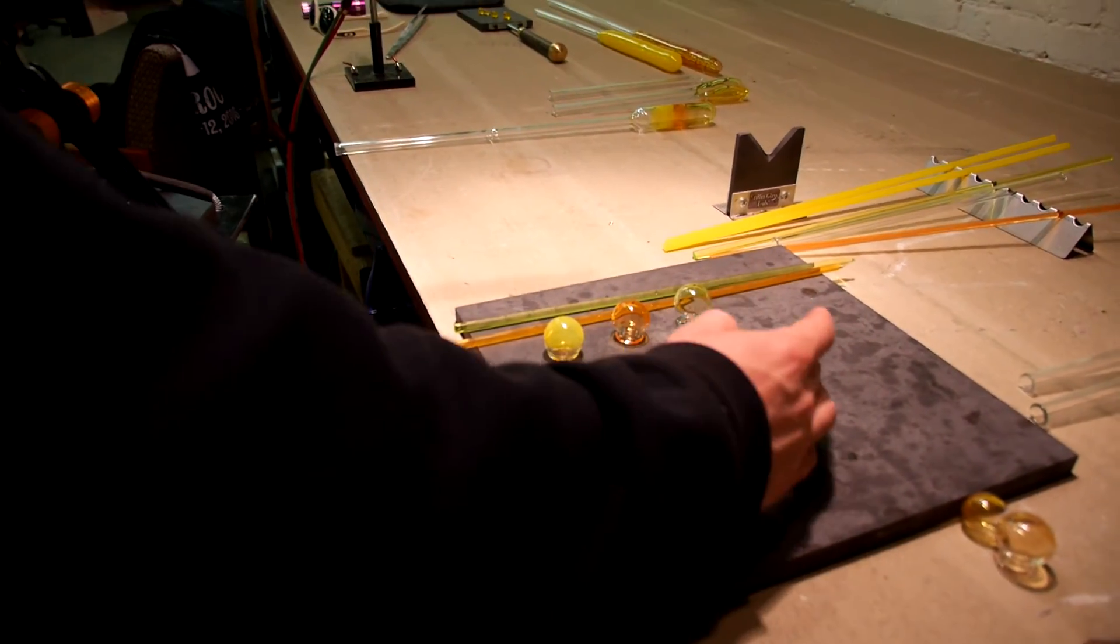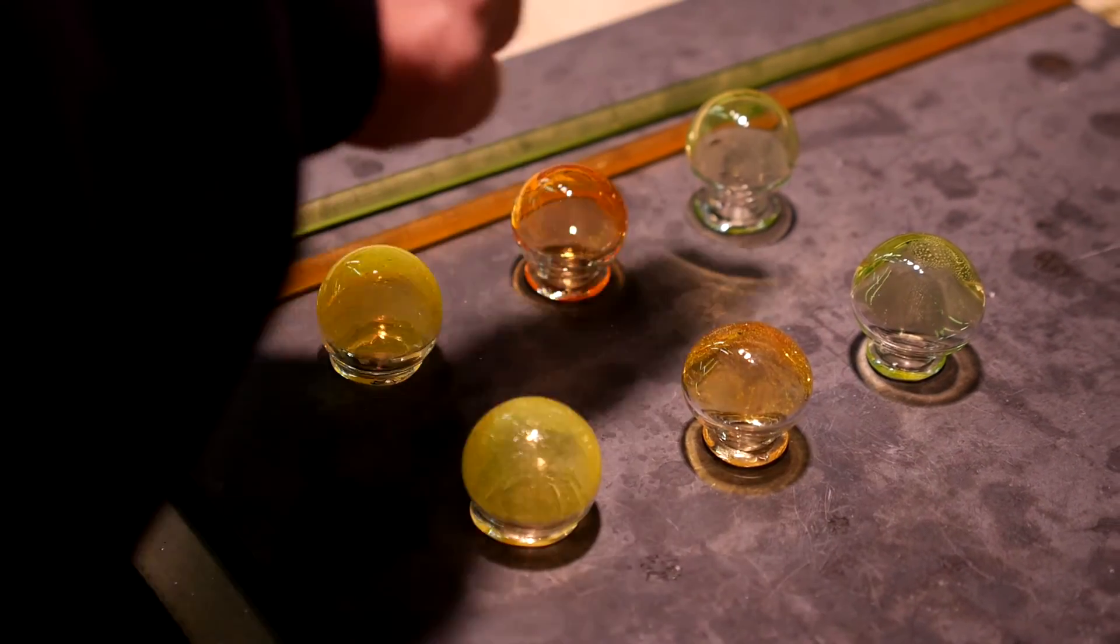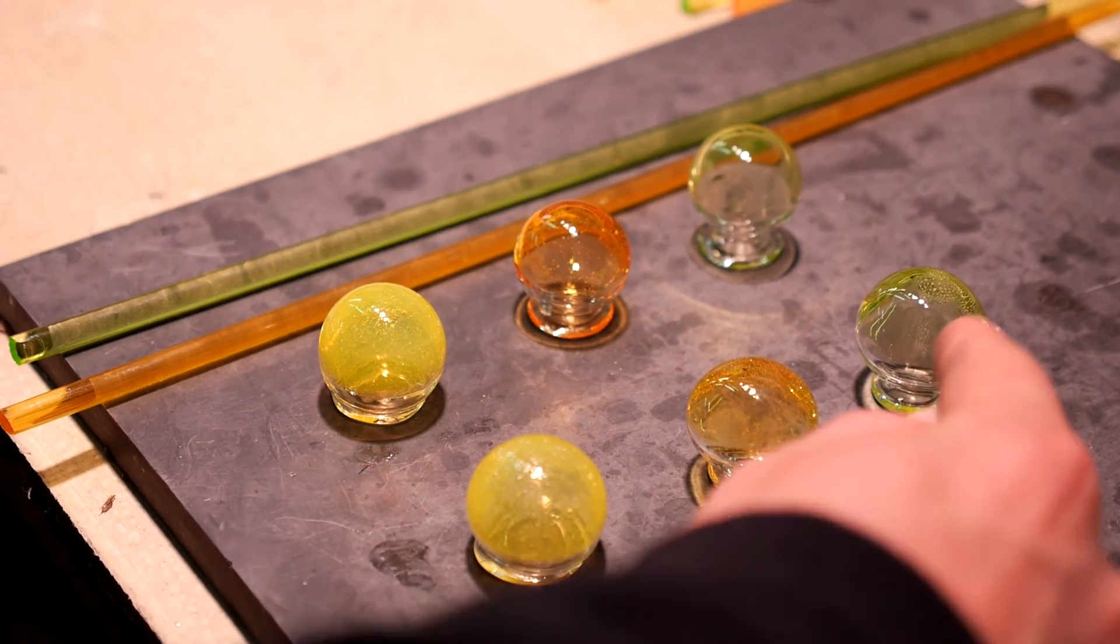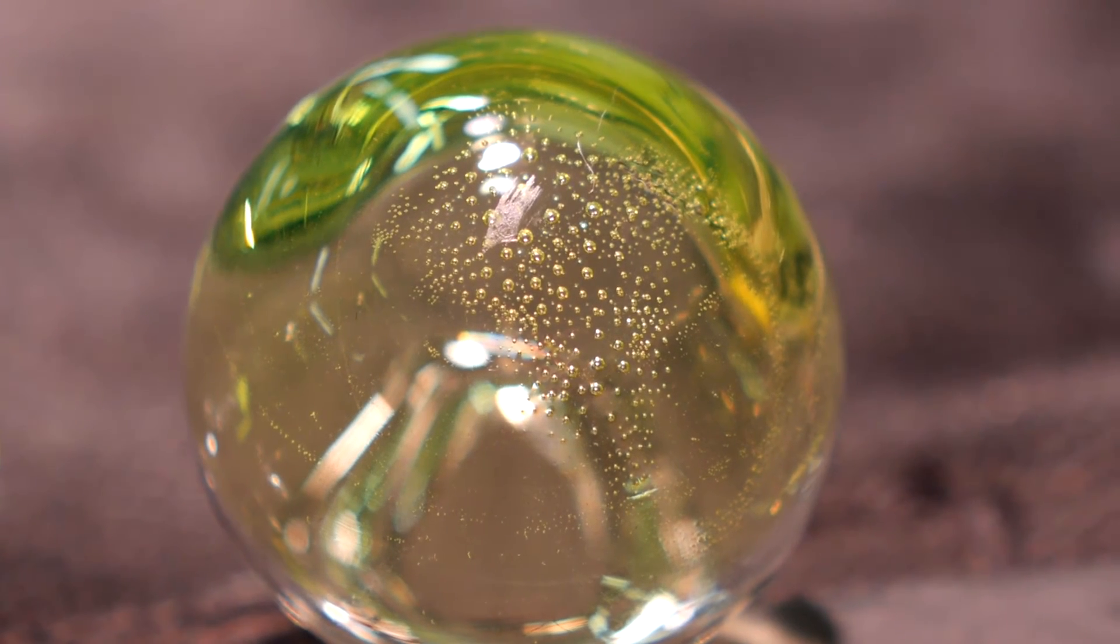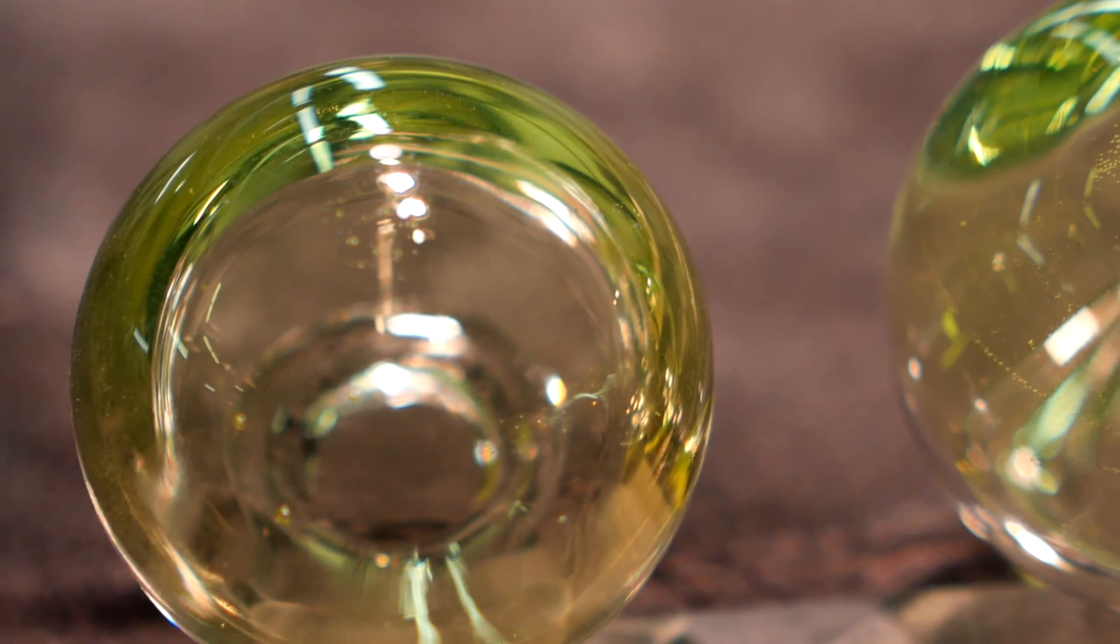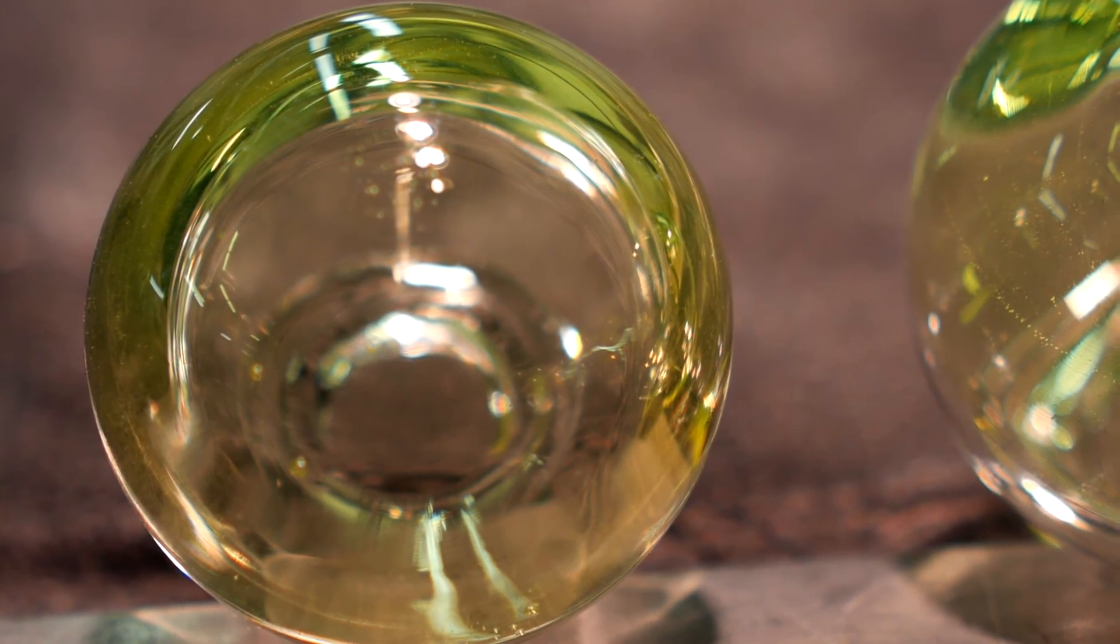I've got a couple of different samples here of Illuminati, Tangy, and Lemon Drop worked with compressed air on the left and worked with a neutral setting on the right. The Illuminati is a great example. We have this bubbling and fizzing that everyone knows you can avoid if you're really, really patient. The benefits of the compressed air are pretty clear in this example.